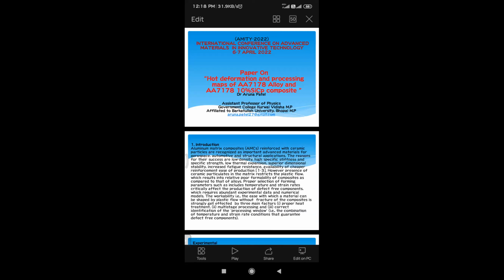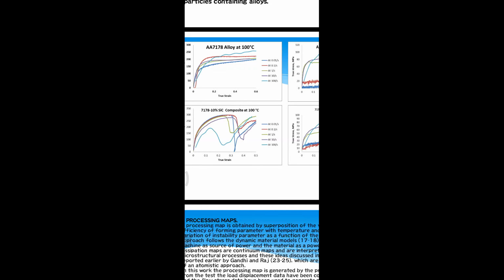So basically you are preparing this composite material for softening the material. I have a bit of doubt about the flow diagram at 100 degrees. This is the flow curves. Yes, sir, the stress-strain curve. I only have a doubt about what it means here. Sir, in the stress-strain curve, 0.01 is the strain rate, meaning the speed of deforming the material. So 0.01 represents very slow pressing of the material, and 100 per second represents high speed.